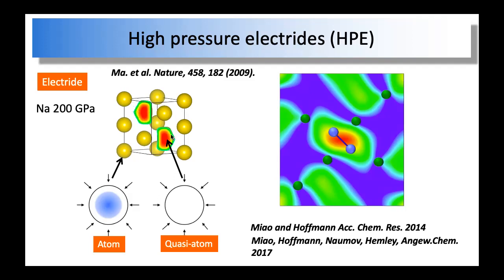But in some of these open sites, if you calculate the number of electrons occupying there, you will find it's better interpreted as singly occupied states. If you have singly occupied states, that means it should be a metal. However, lithium electride is not a metal. It has a small gap of, I think, 0.3 eV, much smaller than sodium.